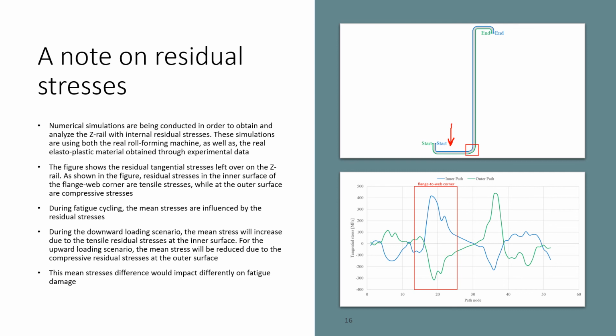So during fatigue cycling, the mean stresses are influenced by the residual stresses. During the downward loading scenario, the mean stresses will increase due to the tensile residual stresses at the inner surface. For the upward loading scenario, the mean stresses will be reduced due to the compressive residual stresses at the outer surface. This mean stress difference would impact differently on fatigue damage.